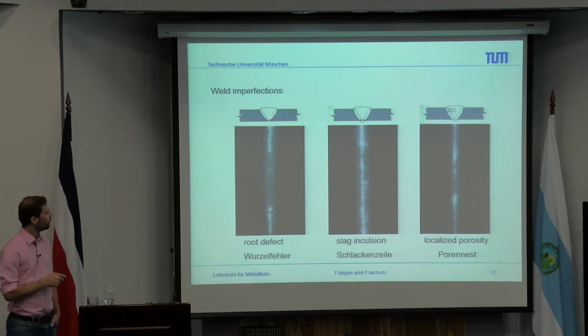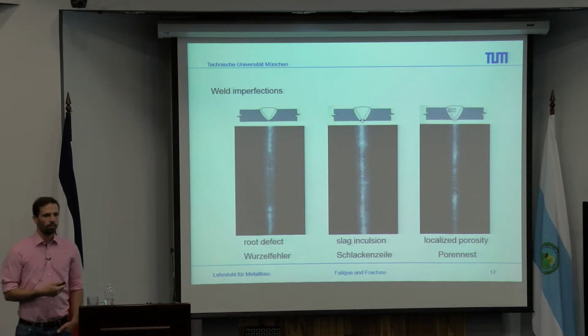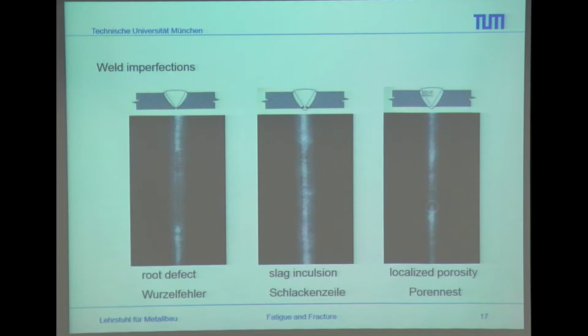So a root defect means that at this part we have the butt weld, which is a V-seam. The V-seam is welded from one side. We have a weld preparation here, and at this part, the welded part is not completely welded. And so the crack is going to start at this point into the material, and in the end the structure also fails.